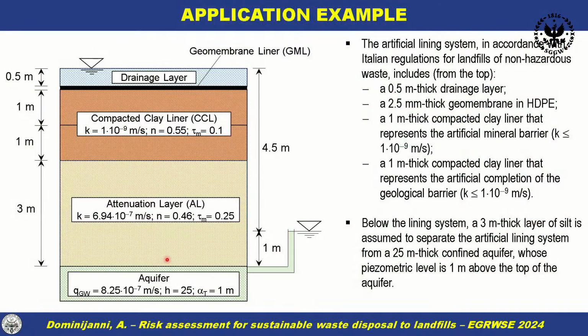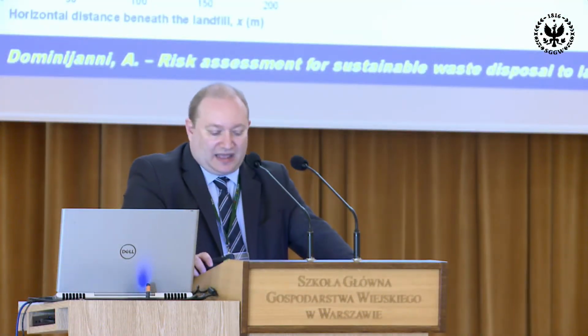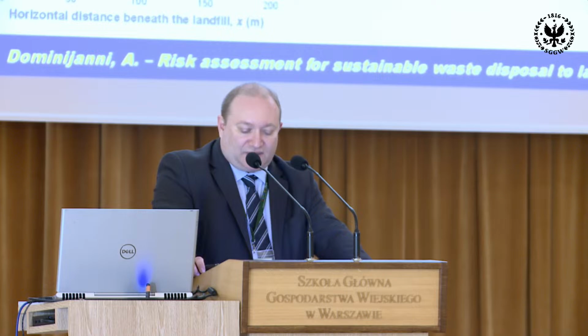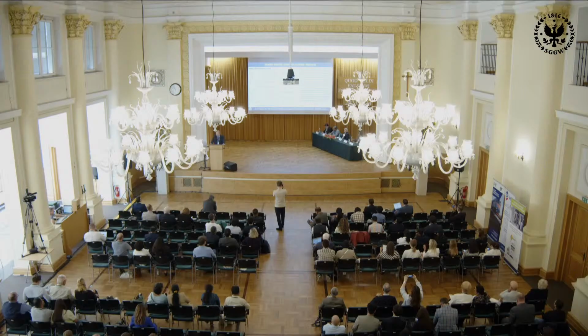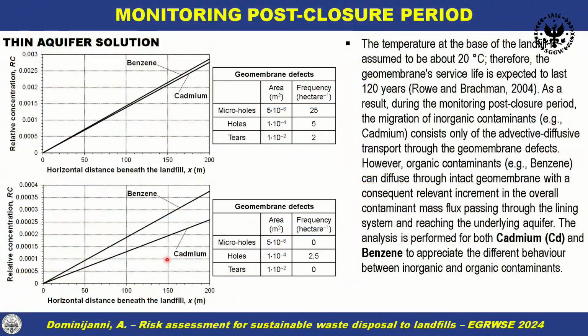Below the lining system, a 3 meter thick layer of silt is assumed to separate the artificial lining system from a 25 meter thick confined aquifer whose piezometric level is 1 meter above the top of the aquifer. The temperature at the base of the landfill is assumed to be about 20 degrees Celsius. Therefore, the geomembrane service life is expected to last about 120 years based on the indications given by Rowe and